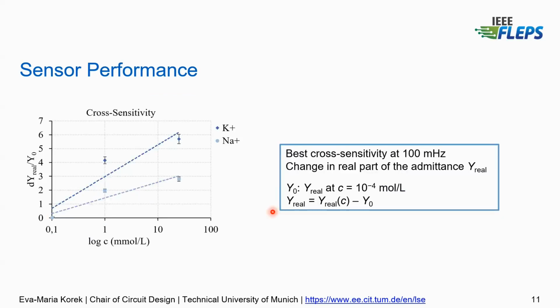Then we checked the cross-sensitivity towards sodium, and we achieved the best cross-sensitivity at frequencies of 100 millihertz. And by looking at the change in the real part of the admittance, we can see by the steeper slope of the potassium ions that the sensor is more sensitive towards potassium compared to sodium.